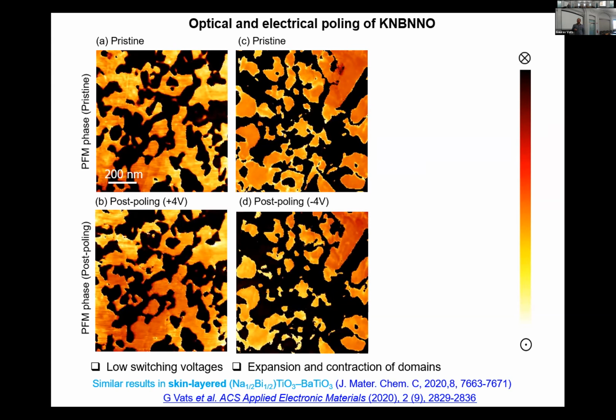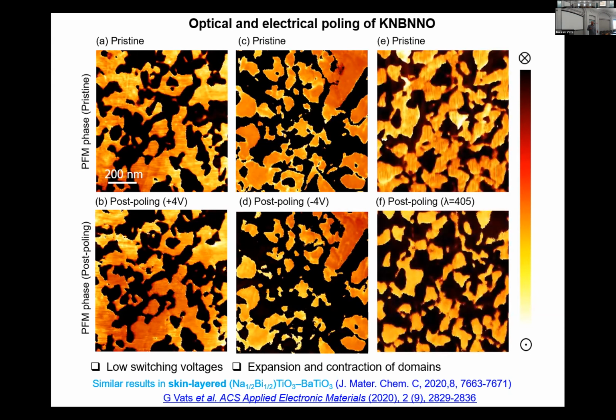However, let's just focus on this again. After this electrical poling, I tried optical poling of the sample. So what I did, I acquired an image in dark, no light was shining. I did nothing, it's the pristine image. And then I shine light on the sample, same wavelength 405, and the yellowish bright domains are shrinking again. If you compare any feature, you'll be able to see the differences. So clearly there is some analogy between optical and electrical poling.